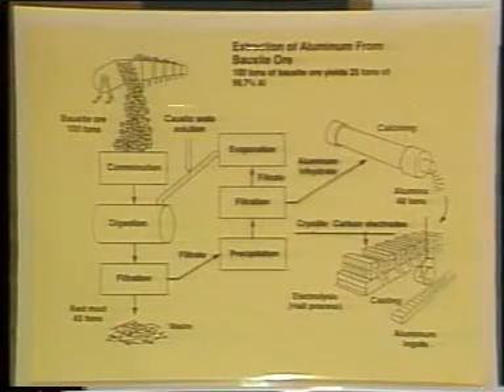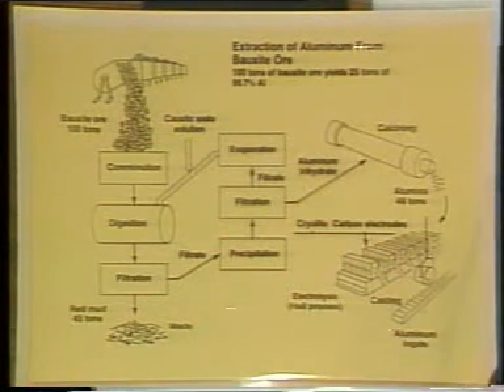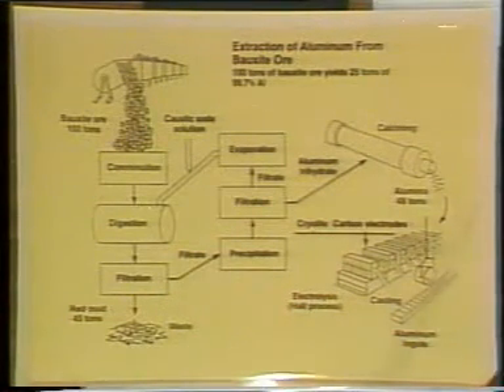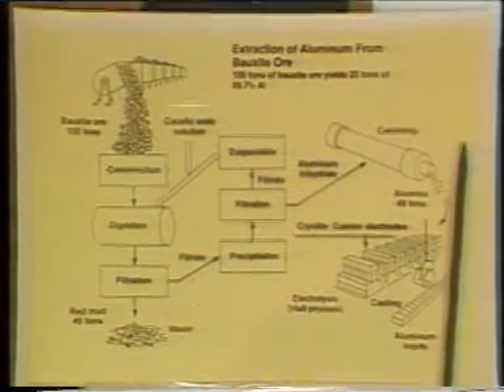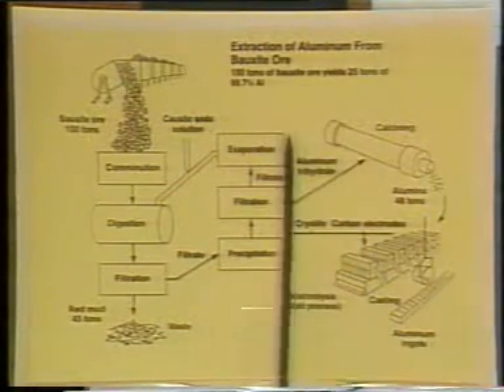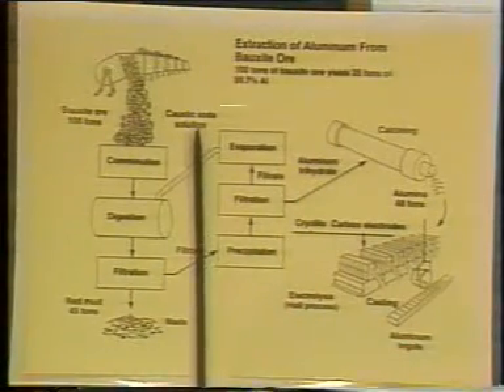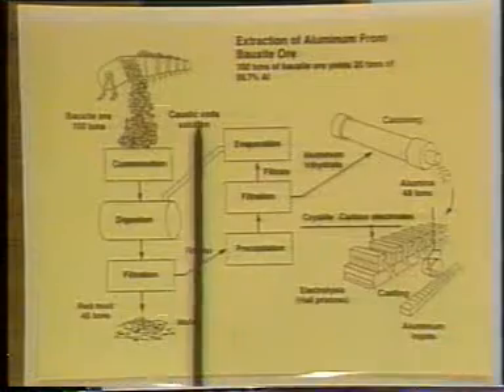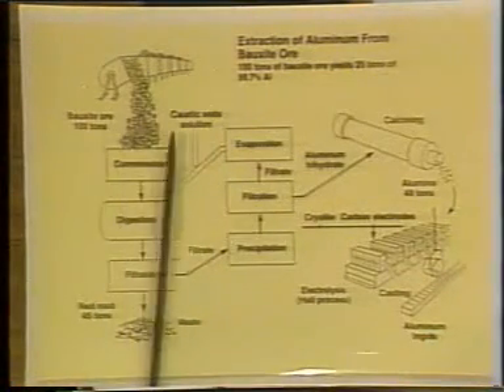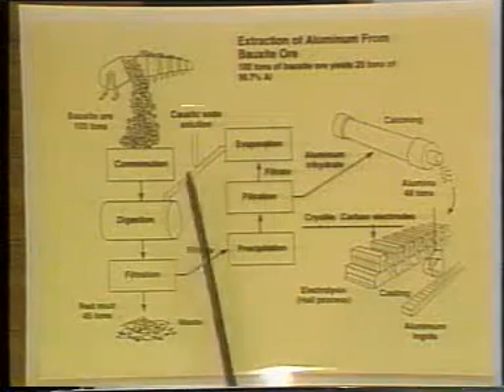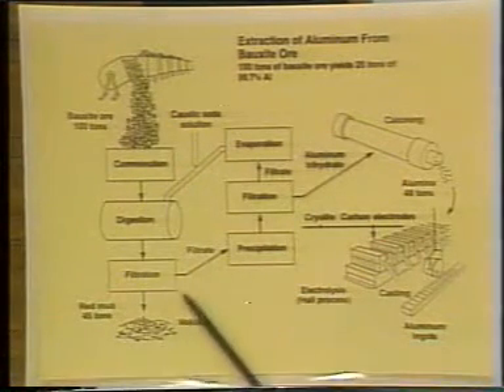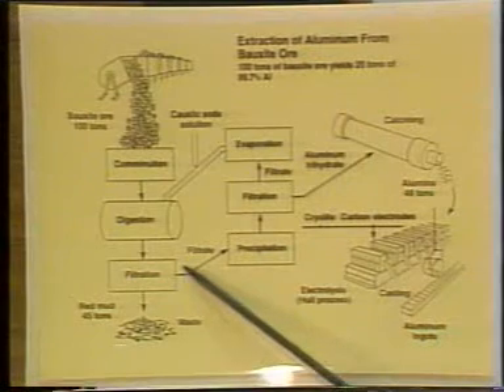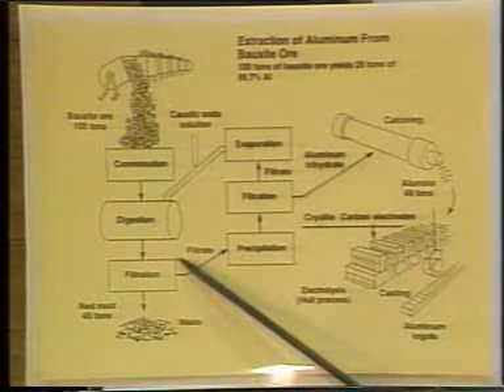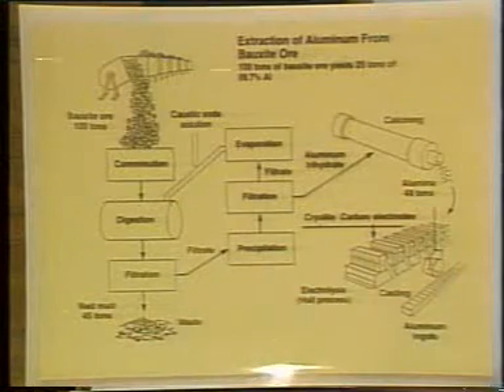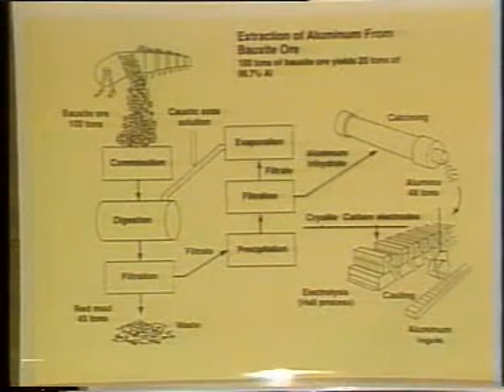Well, let's look at the extraction of aluminum just briefly for a moment and see what we're going to do as a necessary first step. If you want to refine aluminum, what you have to do is refine the ore to oxide. But you notice now we've been talking about doing that right along, even in the gold. So over here, on this part of the chart, we have a process that primarily has to do with purifying the ore, not getting the metal into an elemental form. The trick here is that we're going to use the ability of sodium hydroxide to dissolve aluminum oxide.